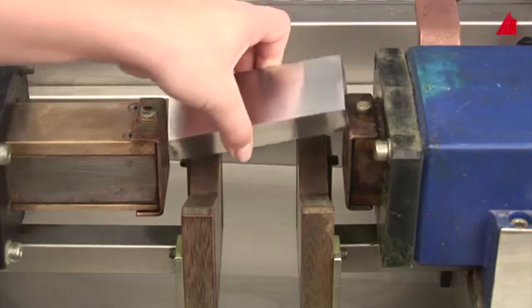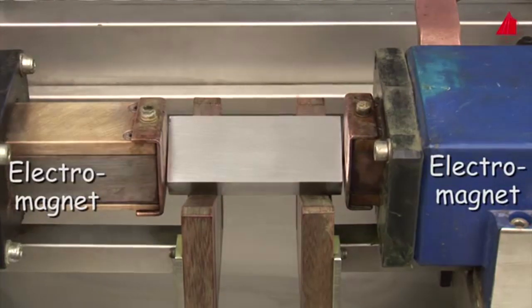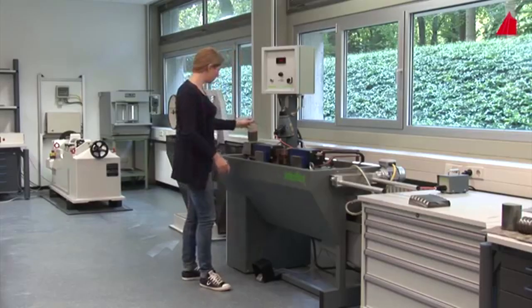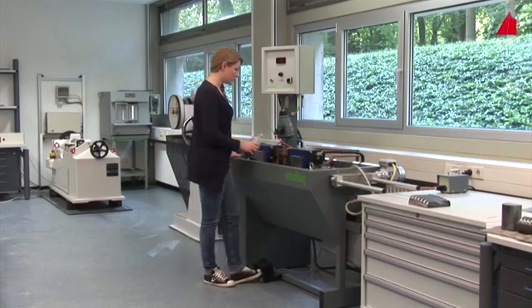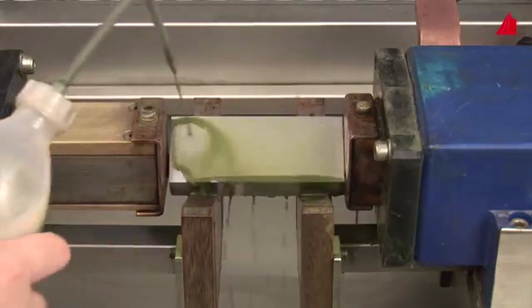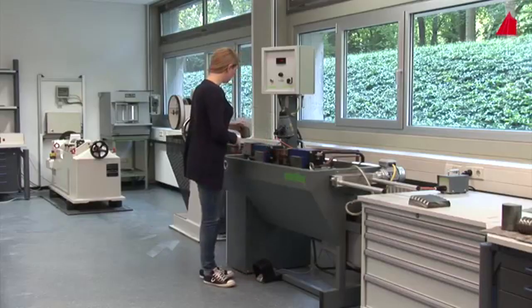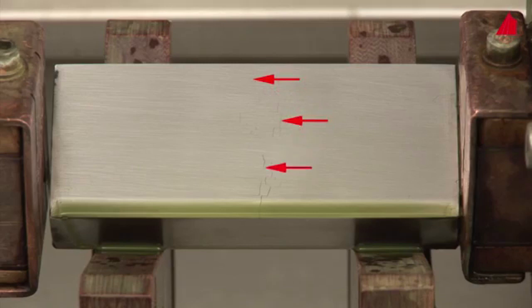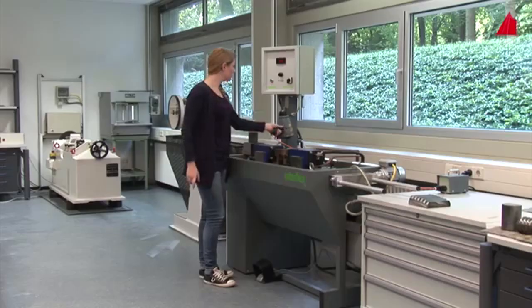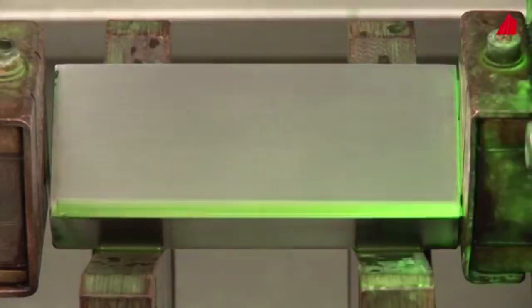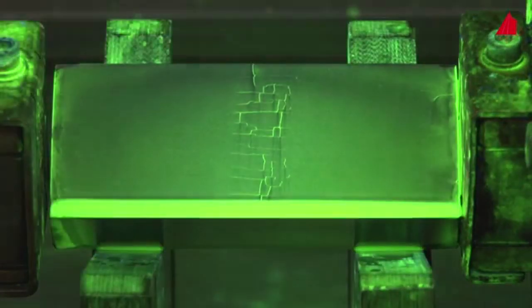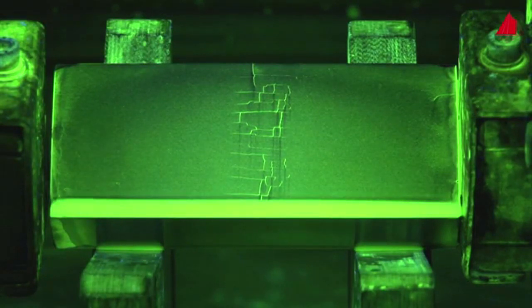The material tester gets the machine ready for use and inserts the test piece between the two poles of an electromagnet. Then she takes a bottle with a suspension of magnetic particles, turns on the electromagnet with a foot switch and applies the suspension onto the test piece. Already in daylight, dark lines are visible on the surface. The lines can be seen much better under ultraviolet light, and particularly well when darkening the daylight. The suspension contains pigments that cover the magnetic particles and fluoresce under ultraviolet light. The particles run off in areas free from defects, and they are attracted and clustered near defects. This workpiece shows a whole array of cracks.